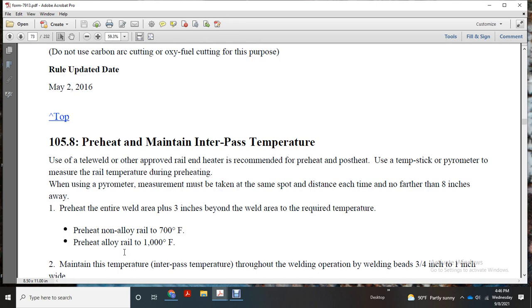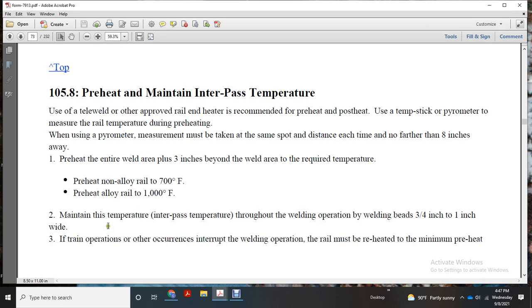The pyrometer measurement must be taken in the same spot with the distance each time, no farther than 8 inches away. Preheat the entire welded area 3 inches beyond to the required temperature. Preheat non-alloy rail to 700 degrees Fahrenheit. Preheat alloy rail to 1000 degrees Fahrenheit. Maintain the interpass temperature throughout the welding operation.